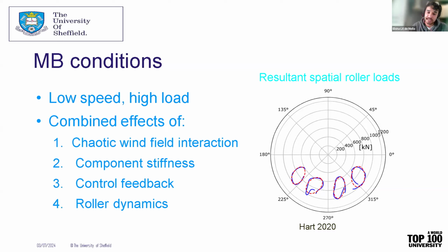These are just a few of them listed here, but when we consider these as a whole, we find that the loads exerted on the bearing from the shaft are circularly looping, 1 to 2 second duration loads that fluctuate and move around the circumference of the shaft. This is a polar plot here, with the angle, and we're getting these loads that are looping around circumferential locations of the bearing. So they're very complex loading patterns we're seeing.